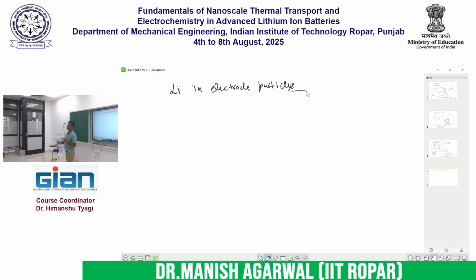Now the funny thing is, after talking about all the things about the homogenization, you cannot do the homogenization for lithium movement in the battery. That is not possible, because the lithium diffusion is actually happening at the micro scale. So what is happening here when I am converting this K1, K2, K3 into this homogenized field? That is fine. I am actually simplifying my problem.